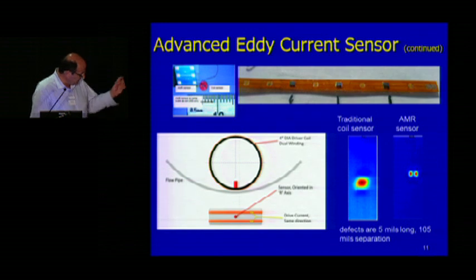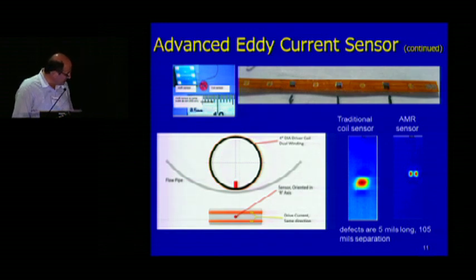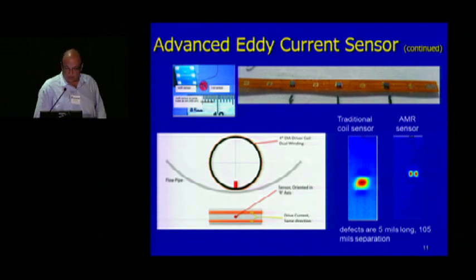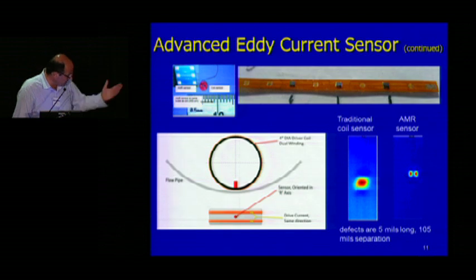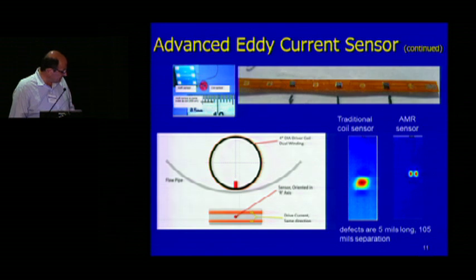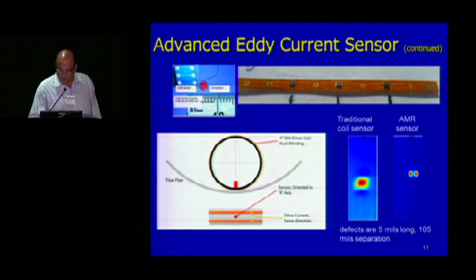The one big red circle that you see is what you get if you use a traditional eddy current sensor, which basically gives you no distinction between the two cracks. And on the right side is what you get with the sensor that we are testing now, where you get a really nice, first of all, detection, and then separation of the two cracks that we're looking for.